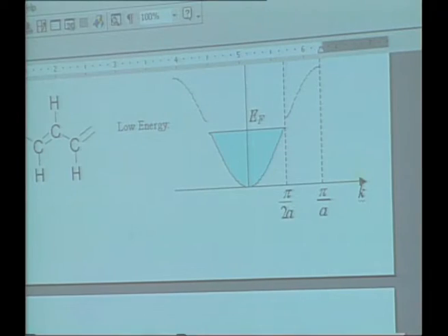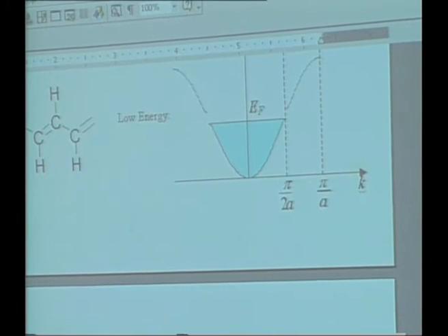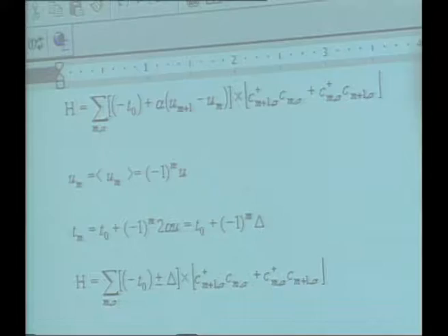It's like that of copper. So these are not delicate, narrow band structures. These conjugated polymers are broadband robust structures with a robust electronic structure. And a story that I will come back to many times, if indeed we could get high degrees of structural order, that should lead to semiconductors which have high mobility. The point I was making here is that because of this broad band structure, in principle, one should be able to get relatively high mobilities. But as we will see in the materials that are available to date, the disorder is too large. We don't achieve those intrinsic mobilities.